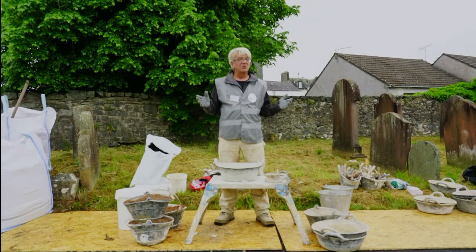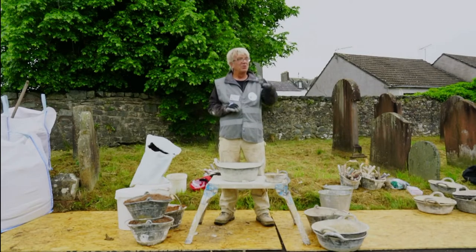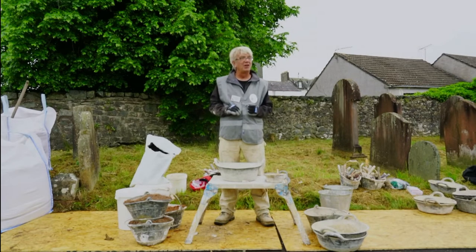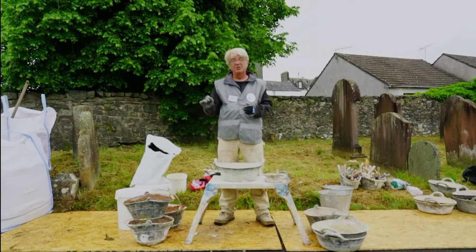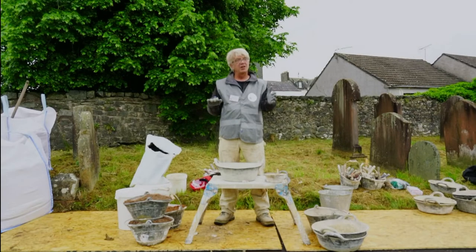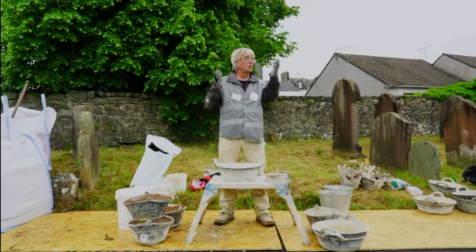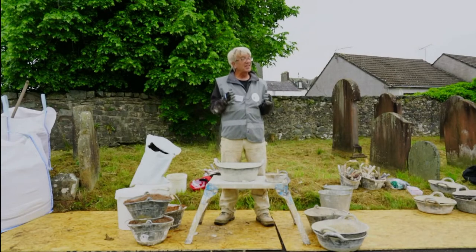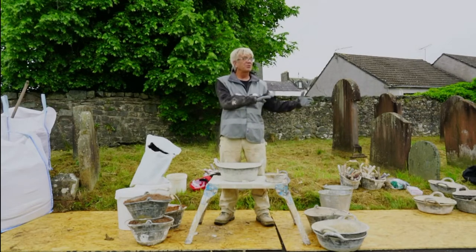In 1951, the Ministry of Works published a four-page or eight-page brochure on lime mortars that's got all the right mortar proportions, really. It talks about cement lime mortars. And actually, when it comes to porous stone, porous sandstone, porous limestone, the mix is pure lime, done with hydrated lime or lime putty, not with hot mixing. But nonetheless, they say that with porous sandstone it is essential, in capital letters, essential to have early rapid hardening, so put in a 16th part of Portland cement. That's a 1:3:12. That's the 1951 Ministry of Works publication.